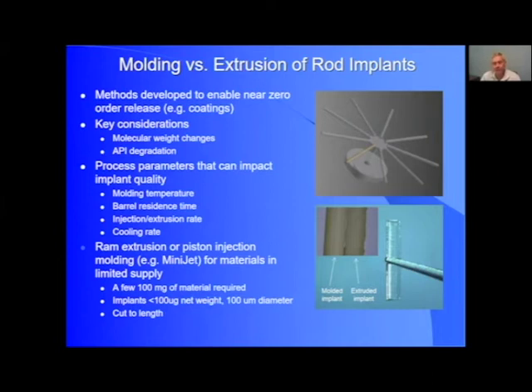You have to keep into consideration the molecular weight change that could happen if you expose it to high temperatures for too long, and API degradation in both cases. So the things that can impact the molded or extruded implant quality are the molding temperatures, the barrel residence time, the injection or extrusion rate, and how fast the materials could cool.